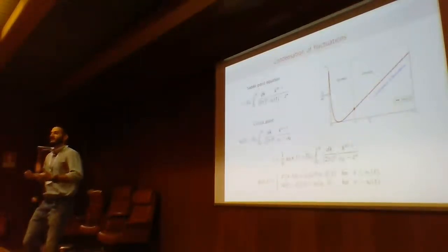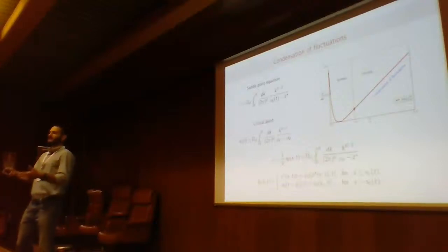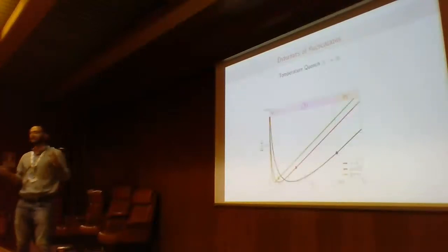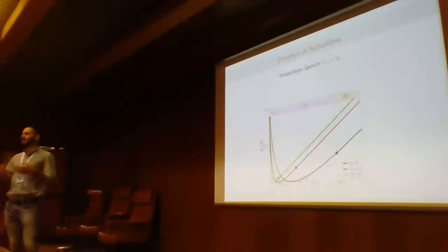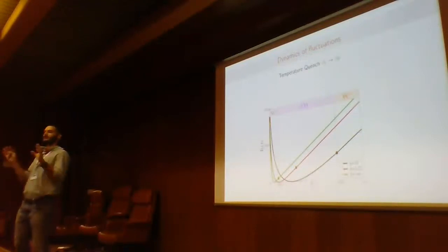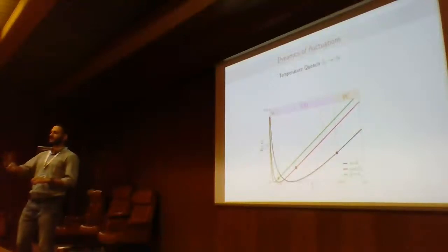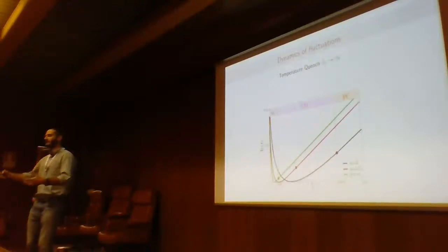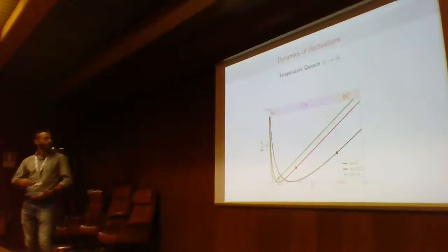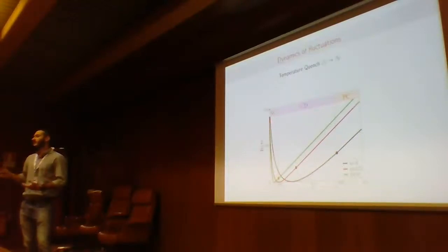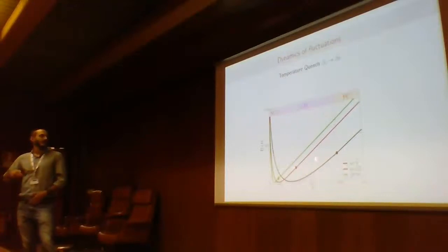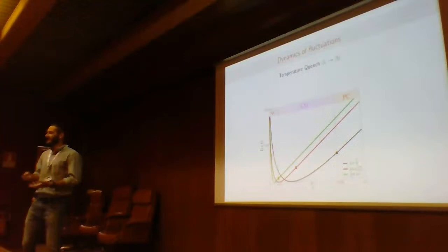There are more interesting things if we go and look at the dynamics. I choose a quenched dynamics. As an initial condition, I put the system in contact with the thermostat at the initial temperature, and then I change abruptly the temperature of the thermostat, and I let the system thermalize. And this is the picture we get. Here we see that there are three regions. One region where fluctuations throughout all the dynamics never get condensed. Here we have a permanent region where the fluctuations are permanently condensed. And here the fluctuations become condensed during the dynamics.